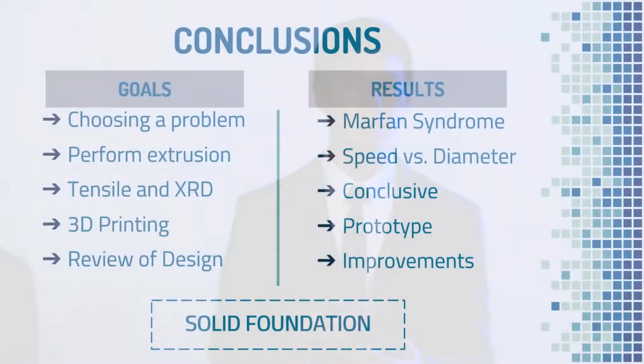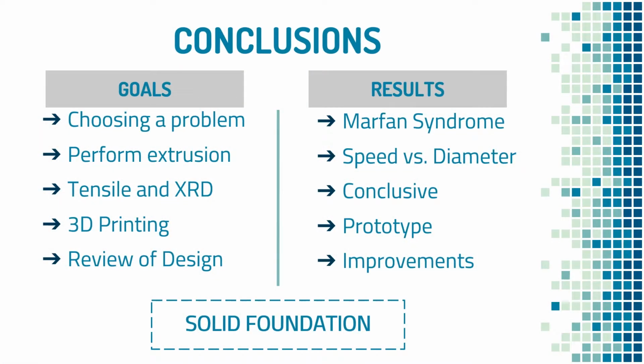So a lot of information was thrown at you, but essentially what we accomplished during this project is, first, we were able to choose a problem with the potential for a more effective solution. That was Marfan syndrome. We performed an extrusion, which helps us establish the relationship between the drawing speed and the resulting diameter of the fiber. XRD and tensile strength testing gave us the relationship between the thickness of the fiber and its Young's modulus, or stiffness, as well as helping us understand the effects of annealing versus not annealing. We have a 3D printed prototype that you can play with later in our demo. And after reviewing our design, we do have improvements to make. Ultimately, we're a long way away from having a marketable device. However, I think we have a solid foundation for future research.